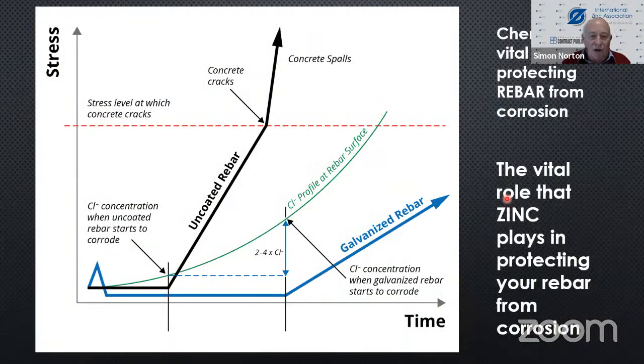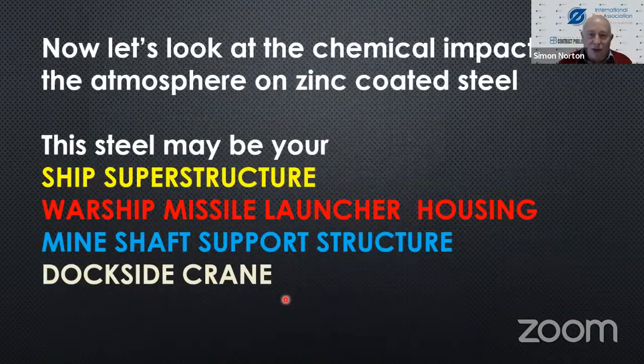If you look at this graph briefly, you'll see that over time, if you've got an uncoated or unzinc coated reinforced steel, you will get to the point where it cracks. If you galvanize it and coat it with zinc, or you zinc thermal spray it, or you even zinc-rich paint coat it, then you'll get a much longer life out of your reinforcing steel. Now, let's look at the chemical impact of the atmosphere on a zinc-coated steel.